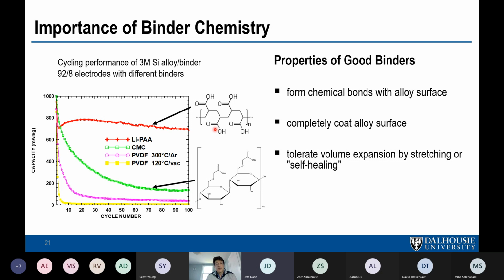Whenever you see a paper that has a conductive binder, you should be aware of the irreversible capacity. Every paper that I've seen that talks about conducting polymers for binders for negative electrodes has a huge irreversible capacity, which isn't discussed. And it's obviously caused by the expensive conducting polymer carbonizing during the first lithiation, which is kind of humorous in my mind.